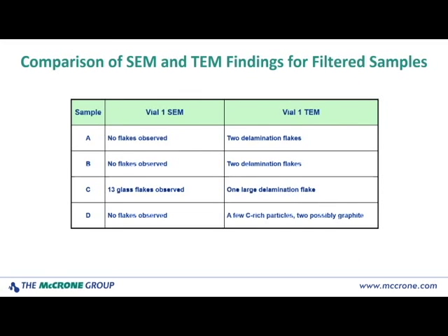We've done some comparisons and some studies using this filtration technique. You have to be careful that there's not background particulate that might interfere with your analysis. So we looked at as received grids. We also looked at blanks prepared in the clean room using our particle-free water. And in both of those cases, there was little to no background particulate on the grids, and certainly not anything that would be confused with the kind of particulate that you would see from glass delamination. So we felt fairly confident that we could move forward with this filtration method.